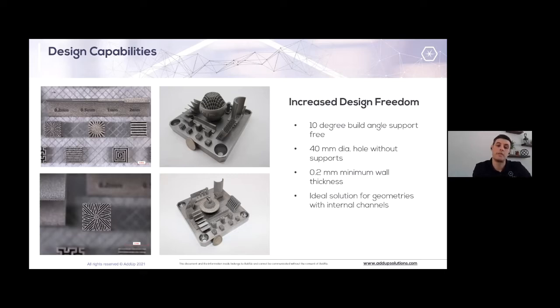So rather than having to build at 45-degree angles without support structures, we can actually get down to 10-degree angles without support structures. It allows us to create very large pass-throughs or hole diameters up to 40 millimeters. We can get really fine feature resolution, 0.2 millimeter thick walls. So this is great for internal geometries or internal channels where you need really fine feature resolution.